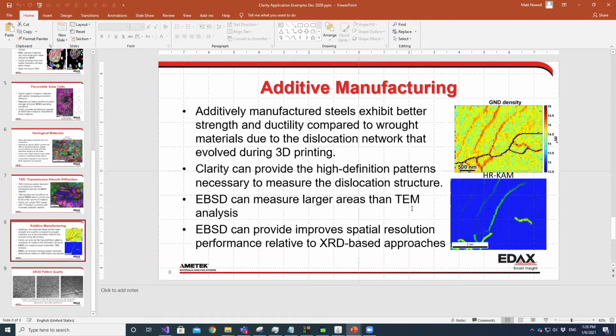And then, of course, one of the big hot topics everywhere is additive manufacturing. This is an example from a stainless steel alloy. We get a rapidly solidified structure with some cellular structure that really helps to provide superior mechanical properties. And so, by using the quality of the clarity patterns, again, they're distortion free, they're blur free, we can do cross correlation results to really improve the angular orientation precision of the technique, and couple that with improved spatial resolution compared to XRD based approaches.